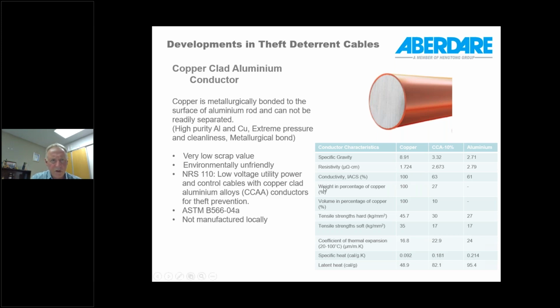If we move on to the alternative conductor material of copper-clad aluminium, I must say that this has also not been successful, and I would say mainly to the extent that manufacturers were not comfortable with the problems associated with this particular conductor and the cables. It's manufactured in a similar way, or in the same way as copper-clad steel is manufactured, and you also need high purity aluminium and high purity copper, because you need this metallurgical bond, which is created in the same way as you do for the copper-clad steel.